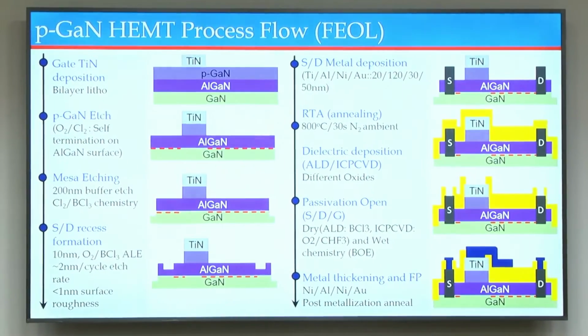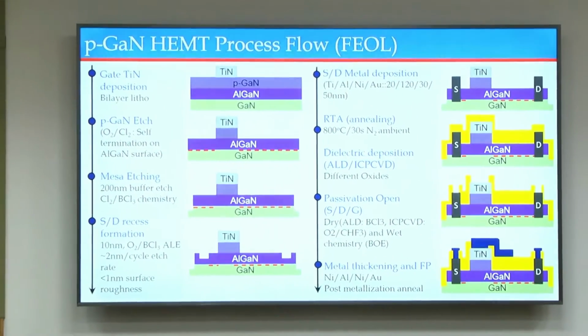And then of course you have to go further, you have to have passivation. In this case, since you don't have a GaN cap, you are etching and now AlGaN is exposed, you have to have a passivation, and the passivation has to be optimized for your 2DEG to behave properly. And then you have field plate design.